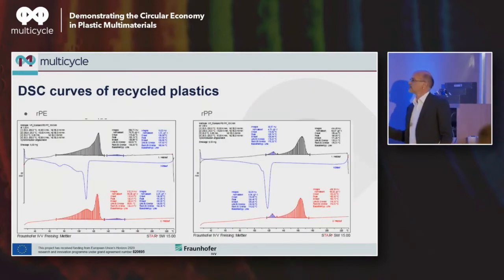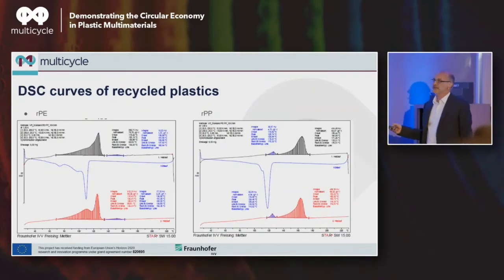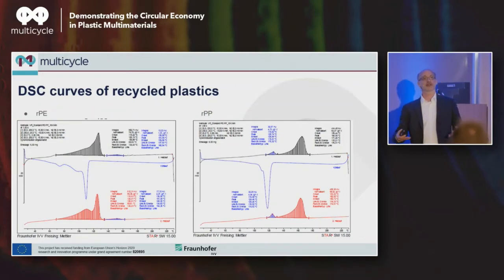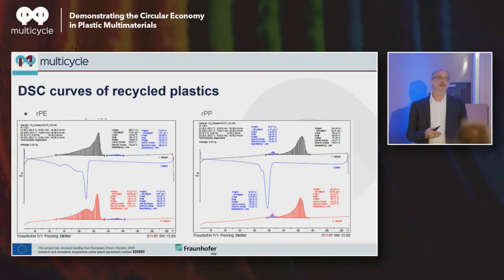Here we see some DSC curves, and even with the very undefined material of this multi-layer post-consumer material, we managed to be in the PE almost PP-free. You see that there's some small residues in there, but we didn't find any larger impacts of that one. But this one is really the quality from the post-consumer packaging waste. Of course, we don't have those issues in the automotive industry.